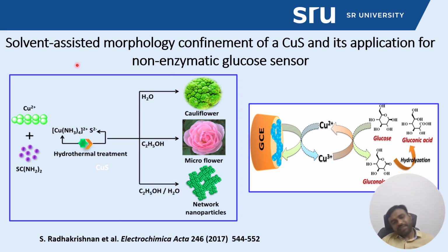So from this schematic diagram, we can clearly confirm that the solvent plays an important role in the formation of the specific morphology, because it has different reactivity, different solubility, and different polarity, which make a clear impact on the formation of the nanostructured product.